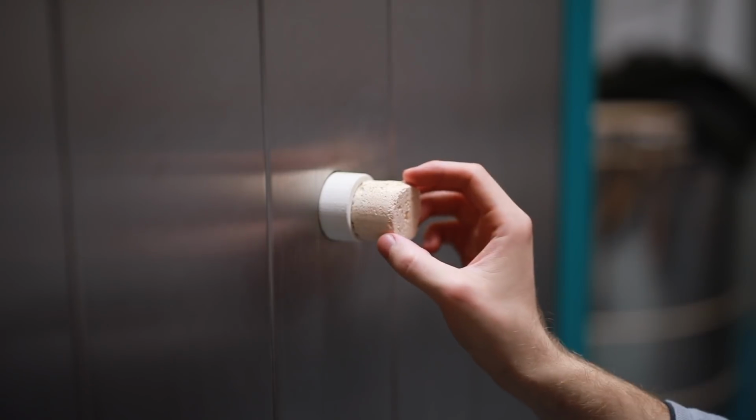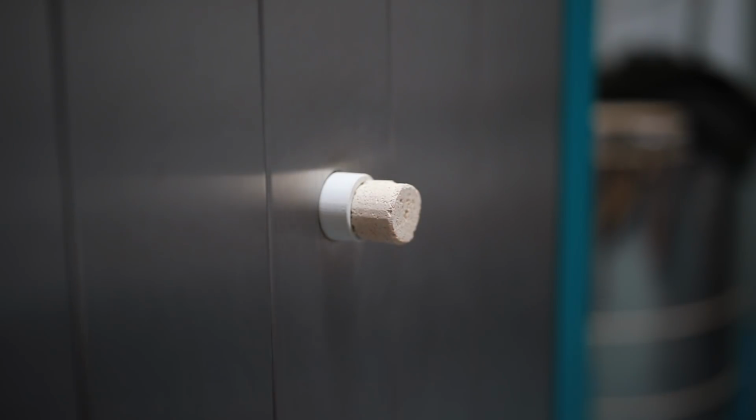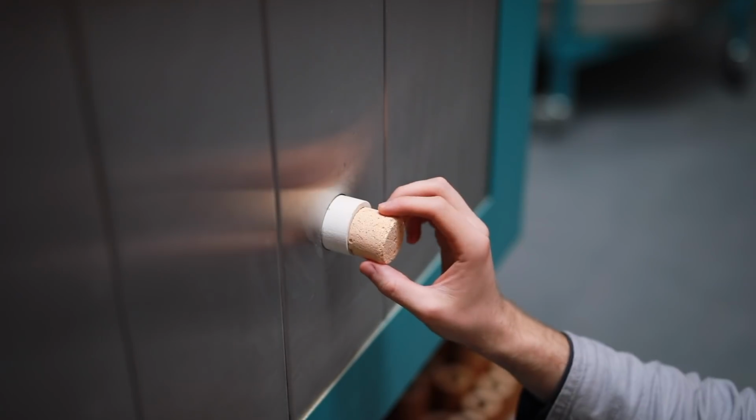If I were to fire my pots in an oxidized atmosphere, one with plenty of oxygen, they come out almost putrid and yellow and not very nice at all. These flames you see are a good indicator of a strong reduction inside the kiln. The flame pops out as it's searching for oxygen to burn efficiently with.